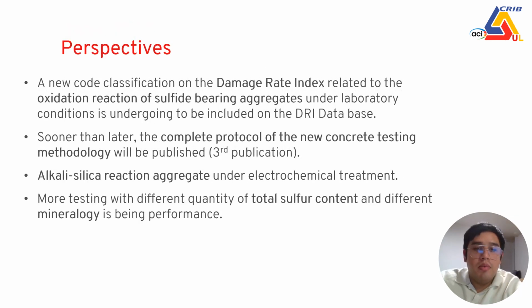In our perspectives, we are now working on a new code for the damage rating index related to the oxidation reaction of sulfide-bearing aggregates. Sooner rather than later, we want to complete our testing protocol with a complete methodology to evaluate the potential oxidation reaction of sulfide-bearing aggregates. At the same time, we are working with alkali-silica reaction aggregates under electrochemical treatment, and more aggregates from different sources and with different total sulfur are being tested with this methodology.